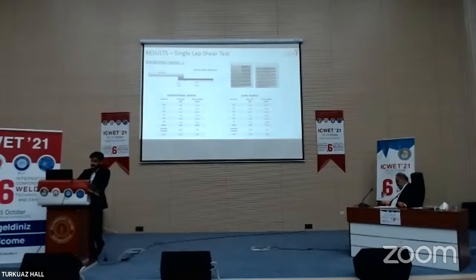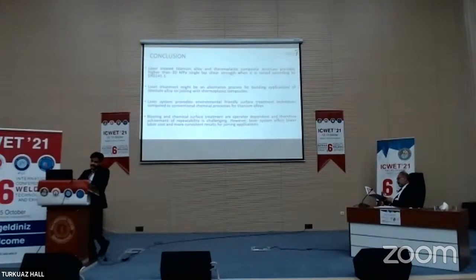As you can see, these results are very similar. When I started to discuss the titanium alloy surface, I mentioned that when we increase the laser power, the activation also increases. If we increase our limitations, maybe we can reach above the conventionally treated single lap shear strength value. To conclude, the laser treated titanium alloy and plastic composite structure provides higher than 20 megapascal.